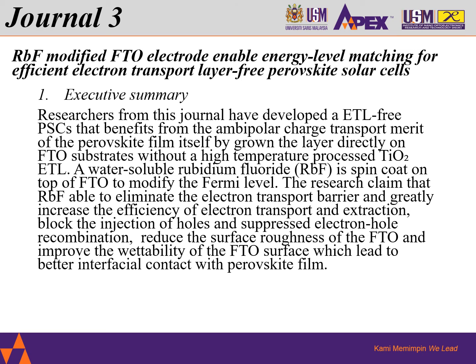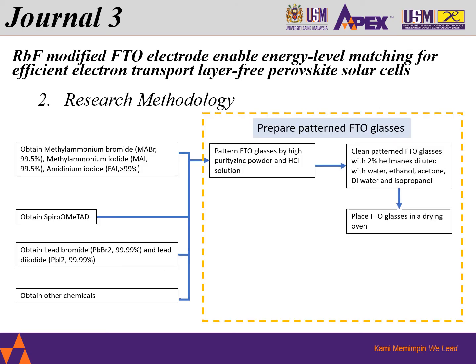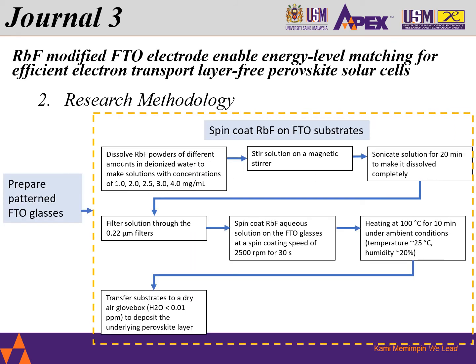The research methodology for this journal is slightly different compared to the other two journals that I have presented, because for this journal they don't have to prepare the ETL layer. They only need to prepare a patterned FTO glass for a better coating of the RbF layer. Once the patterned FTO glass has been prepared, they will spin coat the RbF on this FTO substrate.